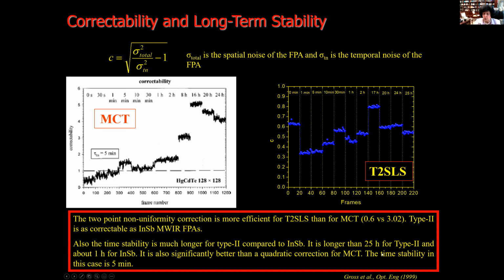It is longer than 25 hours for type-II and about 1 hour for indium antimonide, and at the same time it is also significantly better than a quadratic correction for MCT. The time stability for MCT is only 5 minutes.